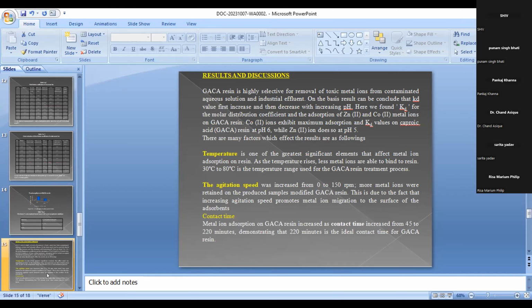There are many factors which affect the result. Temperature is one of the most significant elements that affect the metal ion adsorption of resins. As the temperature rises from 30 to 80 degrees centigrade, fewer metal ions are able to bind to the resins. In the GCA resin treatment process, the agitation speed increased from 0 to 150 rpm, and more metal ions were retained on the modified GCA resins. This is because increasing agitation speed promotes metal ion migration to the surface for adsorption. For contact time, metal ion adsorption on GCA resins increases as contact time increases from 45 to 220 minutes, which is the ideal for GCA resins.